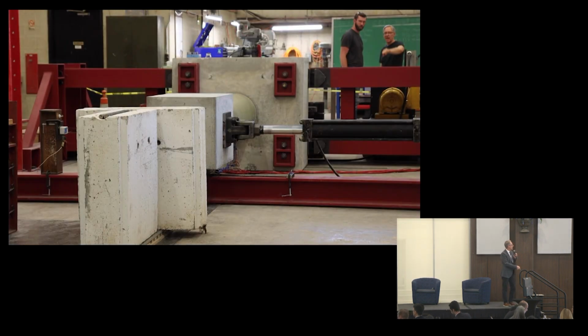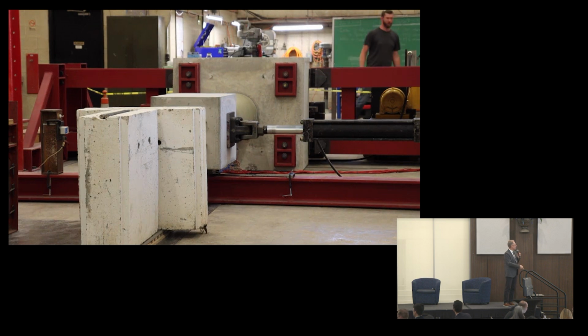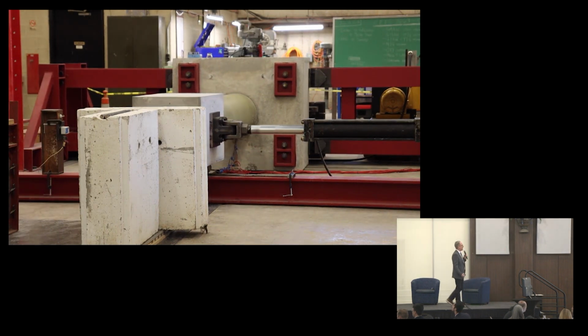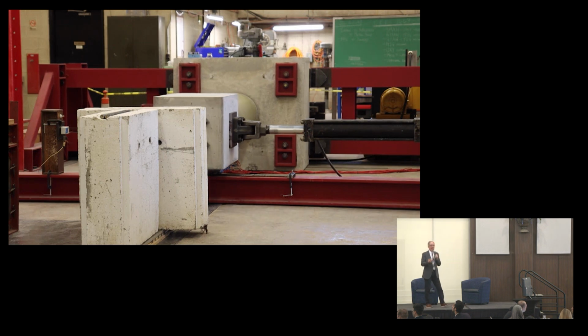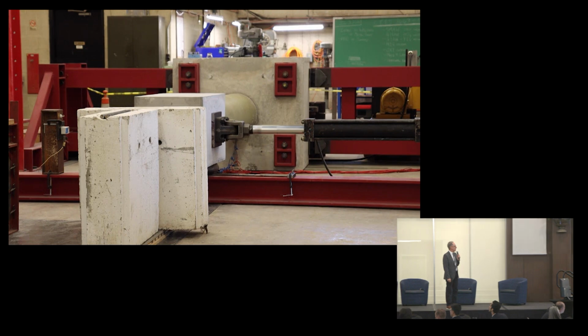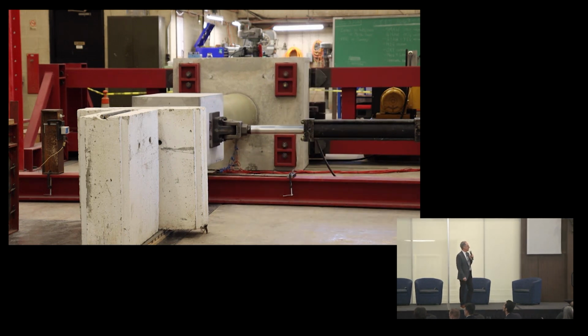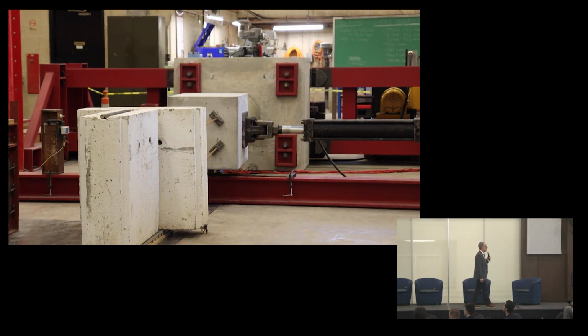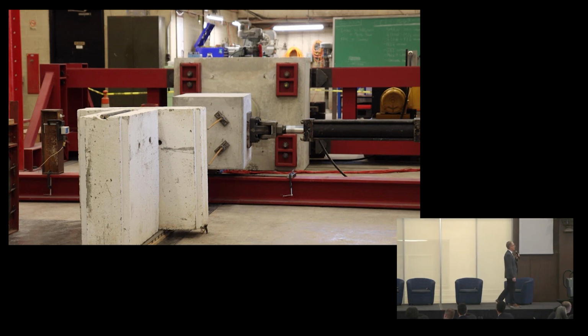And then this is a video of a test. It's a time-lapse photo, pushing it back and forth, just to give you a sense until you see it in person. We had Gary and Walt out during one of our tests to see it, and you see how much we're pushing it, again, a foot in each direction, which is huge for an 8-foot tall column. And yet the one with the UHPC, we could actually not fail. The one with the SCC did extremely well.